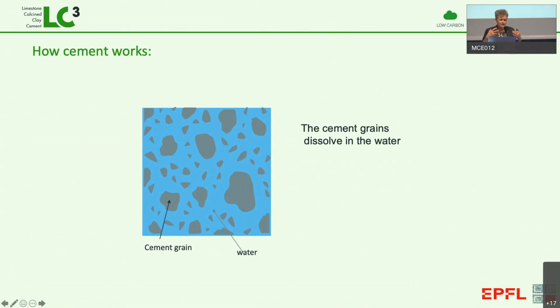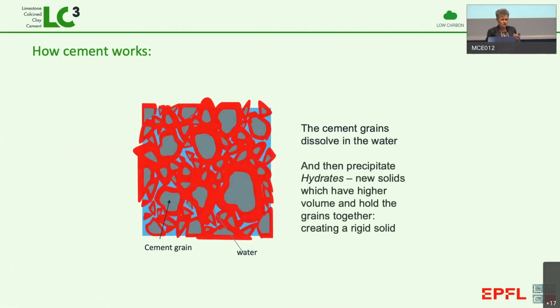Because then you get this chemical reaction between the things that are in the solution, and they form these new solids, which I've drawn here in red, which are called hydrates. And because those new solids incorporate water in their structure, they occupy a higher volume. And because of that, they join the cement grains together and give you this strong, rigid solid. So what you need is something that's going to dissolve, but it's then going to precipitate these hydrates.